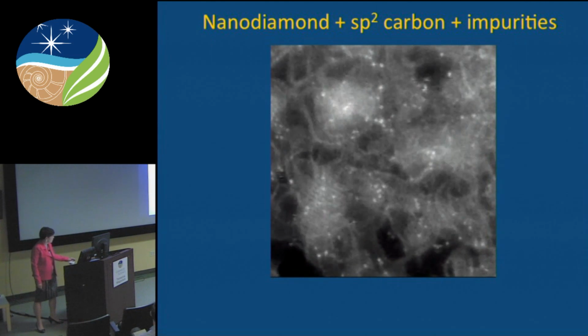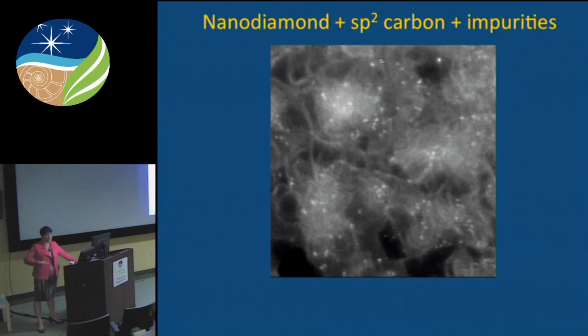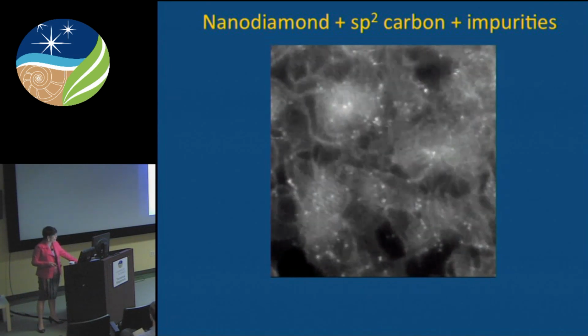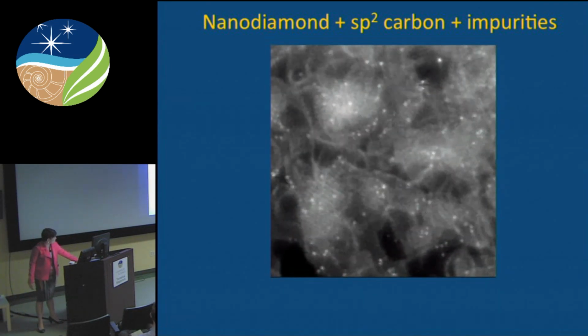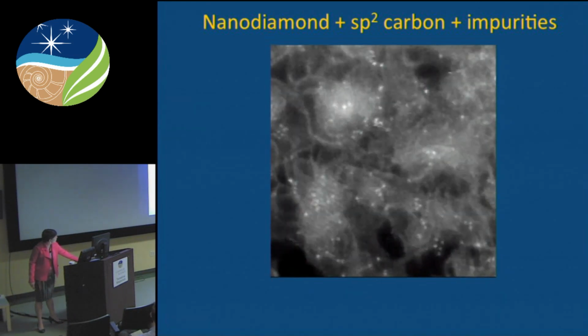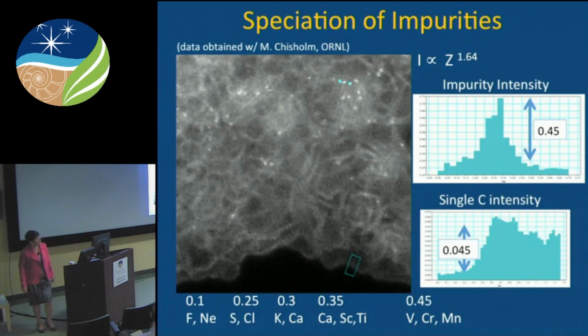This particular movie is a 10 image frame series. Each image takes about 100 milliseconds or so. So you can actually do the dynamics of diffusion in different low-dimensional materials using one of these microscopes. This is at room temperature with the 60 kilovolt electron beam, so there's some energy to promote the diffusion transferred from the electron beam itself.